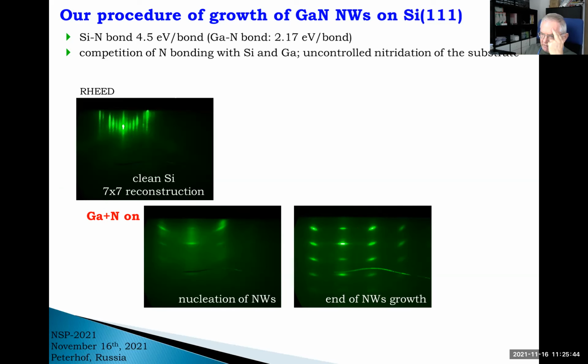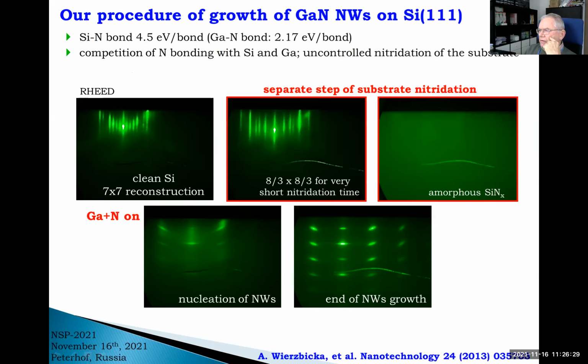However, there's a problem: if we consider the bonding energy of nitrogen with silicon and gallium, you can easily see that the silicon-nitrogen bond is much stronger. So if we open both cells at the same time, there will be a competition between nitrogen reaction with silicon and gallium. And this is something we want to avoid, because there are some reports showing that in this case the silicon nitride film, which we cannot avoid forming on the surface, is rough.